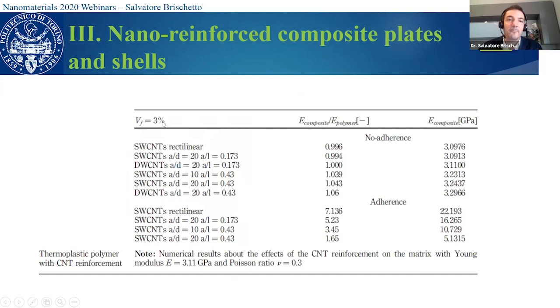For example, for a volume fraction equal to 3%, we have the comparison between single-walled carbon nanotubes which are rectilinear and those which, no, in this case are both rectilinear. The first one is rectilinear, the others are single-walled or double-walled with an appropriate curvature. But we can see that if there is no adherence between the carbon nanotubes and the matrix, the properties do not improve with respect to the original polymer. We need the adherence, okay? And we can see the difference between a rectilinear carbon nanotube and the other types.